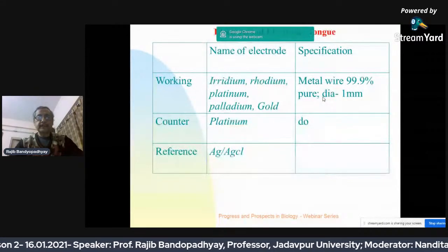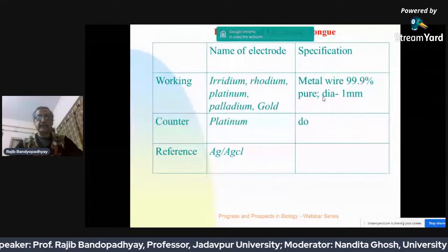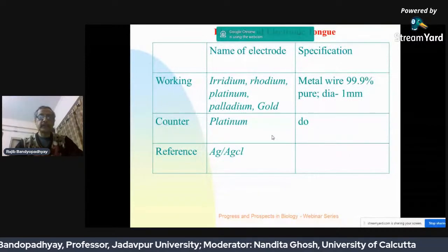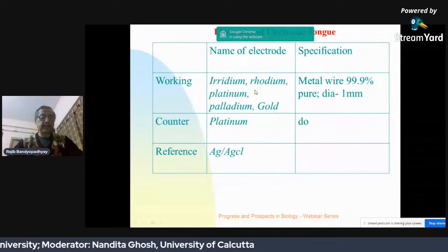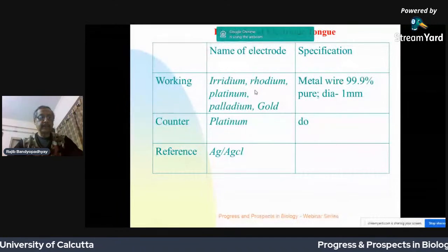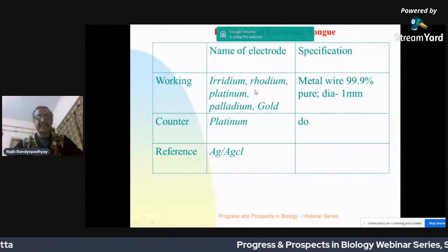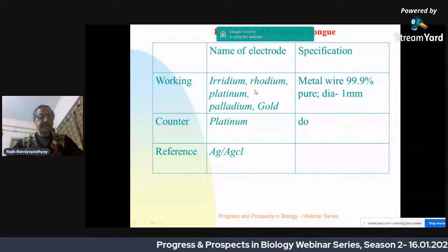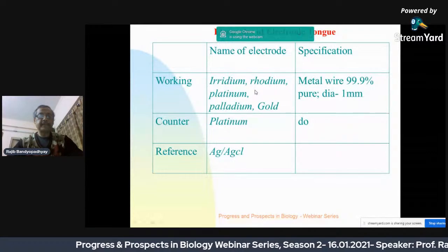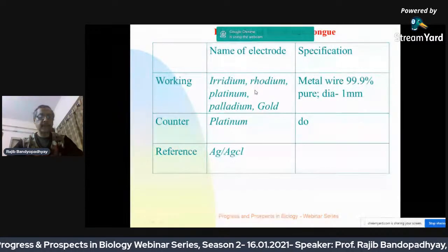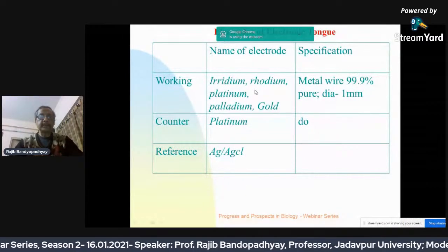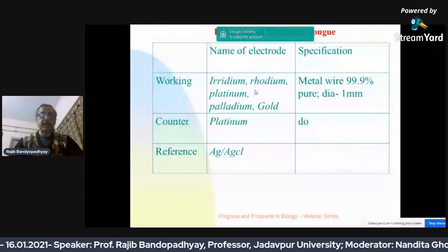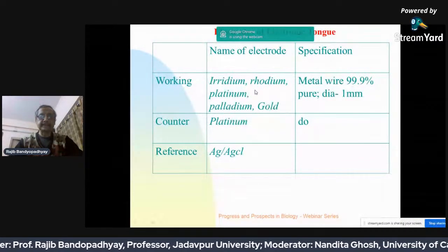So these are the 5 working electrodes that we used for our electronic tongue. These are noble metals, iridium among them. One major advantage of the noble metals is that they are not corroded, and we can wash them easily. We can use them several times, but they do not have any specificity. That's one major issue. But nevertheless, since we get different responses from different electrodes and for different types of voltages, we could get some idea about the analyte by analyzing the data.